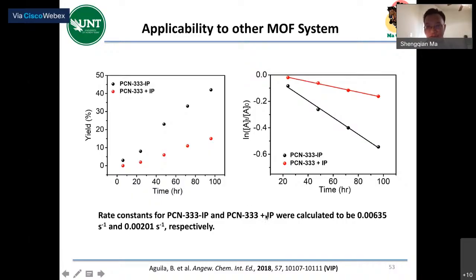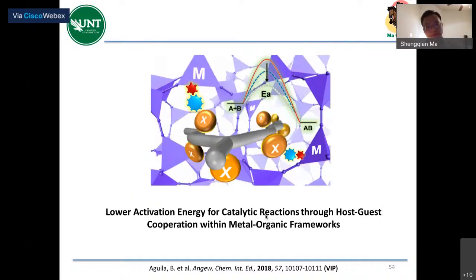This is much faster, with a much lower activation energy. So this is a proof of concept. We demonstrate we can use this to mimic the enzyme, right? Use the host-guest cooperation. We can dramatically lower the activation energy. We use this CO2 cyclization because CO2 now is a very important issue, and also we can easily extend this strategy to other catalysis systems.